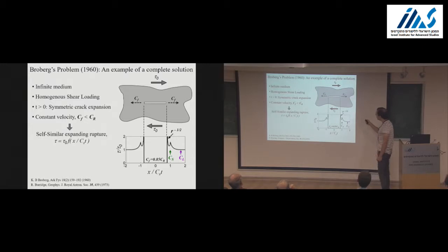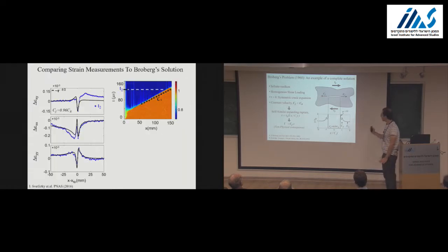So for example, I'm plotting the shear stress along the crack line. This is the crack tip. This is the universal square root singularity. And just ahead of the singularity, there is a prominent shear peak, that I guess you see where I'm going with. Before that, I just want to note this is quite a simple problem, or too simple. It results in fracture energy which grows linearly with propagation distance, which is not observed in our experiments, but I don't have time to go into the details.